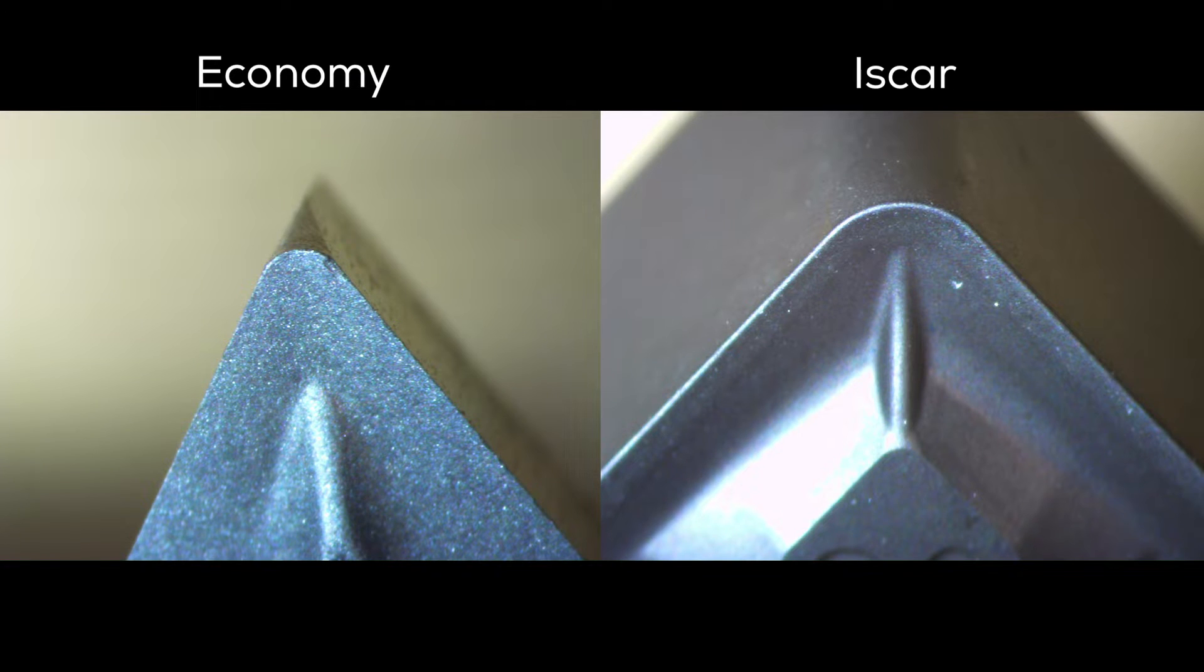And then on top of that stronger carbide substrate, there's also several layers of very hard coating. This is a TiAlN coating, and it's much harder than the carbide, and I think just overall makes for a more durable insert.